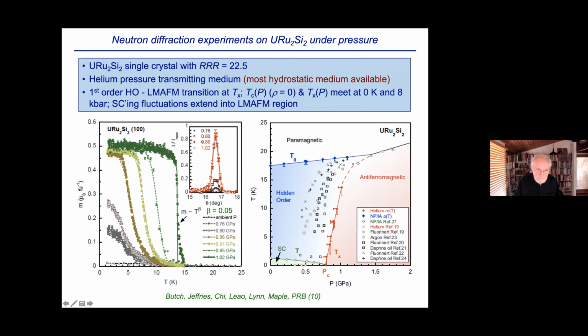Here are some more neutron diffraction measurements made under pressure by Nick Butch and co-workers. Nick is one of my former students. He's done a lot of beautiful other things recently in addition. And this is a single crystal with a residual resistance ratio of about 22.5. The pressure transmitting medium is helium. It's the most hydrostatic one available. And basically what you find is a first order hidden order to large moment antiferromagnetic transition along this line here, which we call T sub X. So you can see the magnetization jumps up very sharply when you get into this magnetically ordered phase. And so the phase diagram then has a hidden order region, a superconducting region here, and then the large moment antiferromagnetism. This is a line of first order transitions.